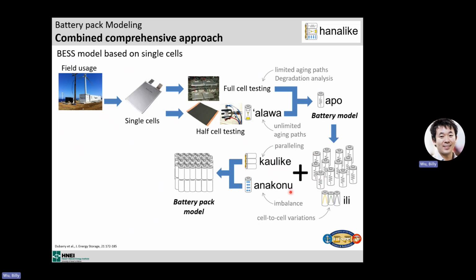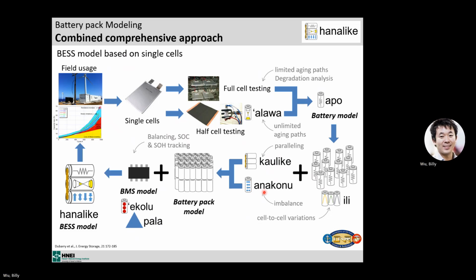And we also developed a model to track the imbalance. It's a really simple model based on measuring 2 rest cell voltages. So if you know the rest voltage of all the cells in the pack, at 2 points fairly close, you can quantify the imbalance. Don't have really much time. I love that model, but if you're interested, we have a paper on it. And then try to control that battery pack, so the battery pack is realistic. And we think that with that, we have a battery pack model that is extremely flexible.